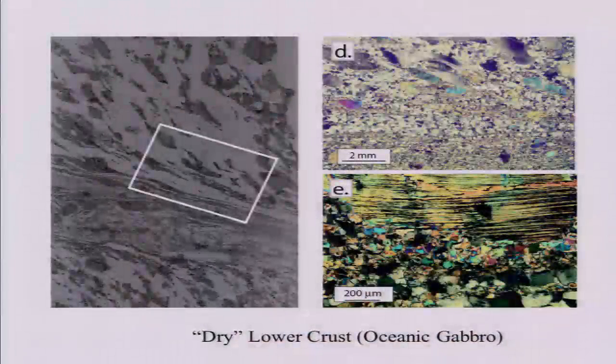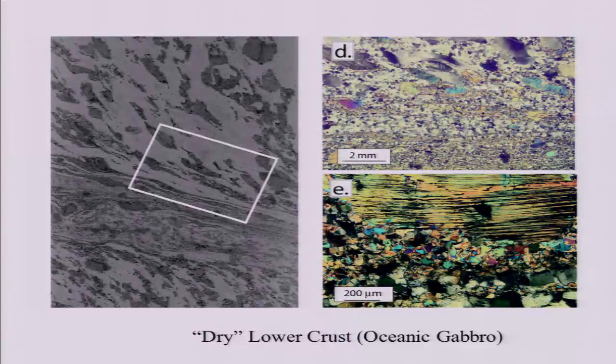They have beautiful microstructures indicating deformation in the lower crust. And what's really helpful about them is that because they deformed at a mid-ocean ridge under a very, very high thermal gradient, they're quenched, so they're only at high temperatures for a very, very short amount of time. The other thing that's nice is that the petrological aspects of pyroxenes and gabbros give you a very good way of determining temperature. And then you can also look at the deformation microstructures to check on the flow laws.